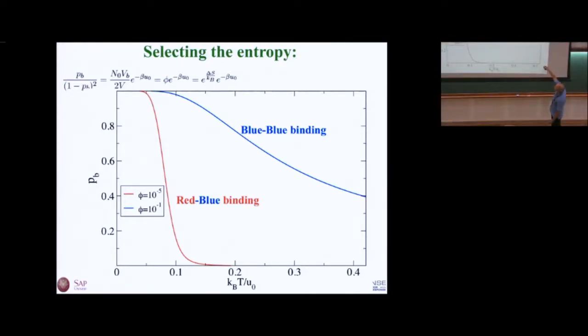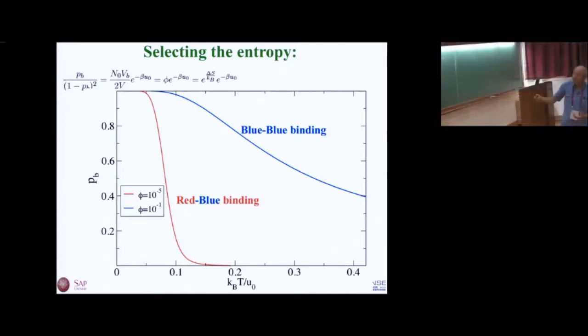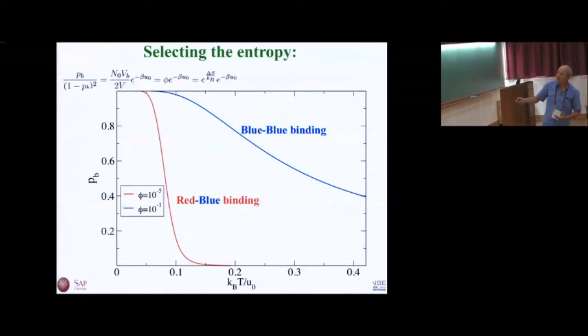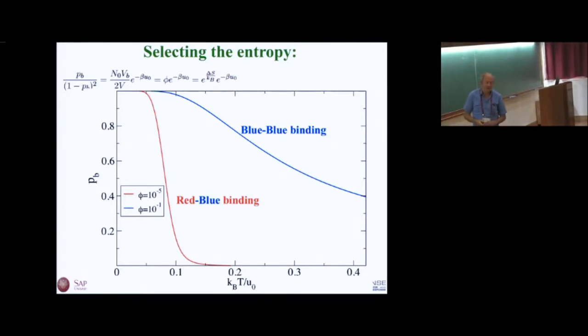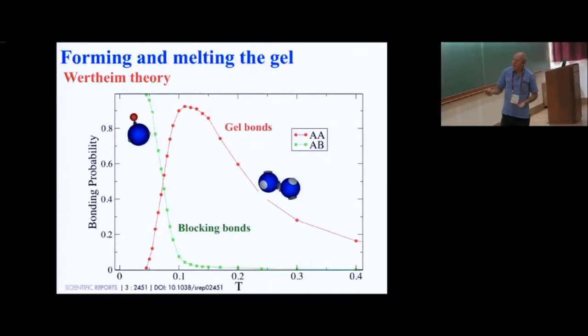This is the idea. If we come from high temperature, we want to first form a lot of blue-blue bonds, and then when we have very low temperature, we want to have a lot of red-blue bonds. We have to play with the entropy. We have to find a way to increase the entropy, so this means the bonding volume, in such a way that this becomes the most stable state. And on the computer it's easy. I can control this bonding volume and fix everything I want.